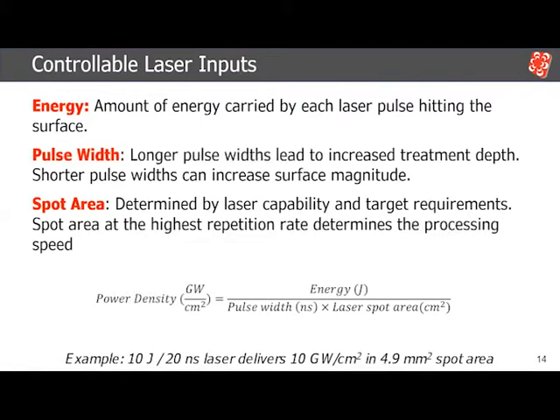So now how can we control these compressive stresses? In laser peening, we have full control over the laser parameters, namely how much energy each pulse generates, and what the duration of that pulse is, which is mainly measured as the full width half max of that pulse. The final parameter is the spot area, meaning the area of interaction of the laser on the material itself. All these parameters combine into one parameter called the power density. In easy terms, the power density is how hard I am hitting the material.